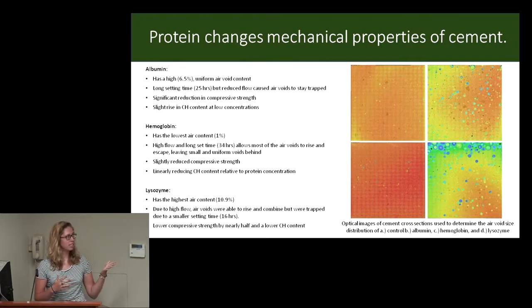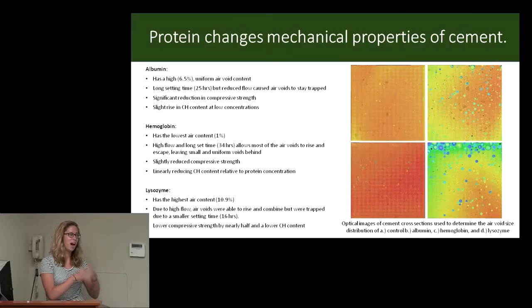For albumin, we saw a high increase in the air content. As you can see, it went up to 6.5%, which is far greater than normal cement. It also increased the setting time and decreased the flowability, which allowed the air voids to remain trapped in the cement. Hemoglobin was very similar. It had a very high foaming ability, but a very low air content because the flowability was so high and the setting time was over 30 hours that all the air was able to escape.